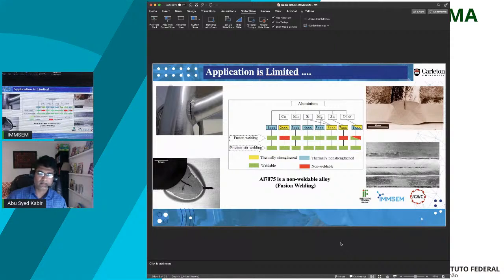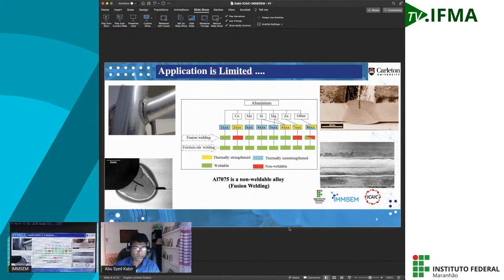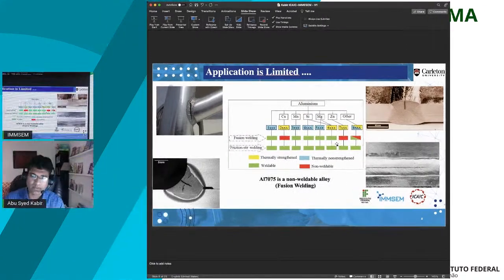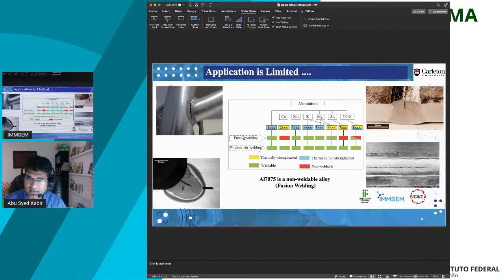Now, still, we know that 7075 has better strength than some of the mild steels, but still the application is limited because of the weldability, especially during the fusion welding. So this plot says which aluminum alloy is weldable and which one is not. And you see there is a big red block here on 7000X. It says it's not weldable in fusion welding.